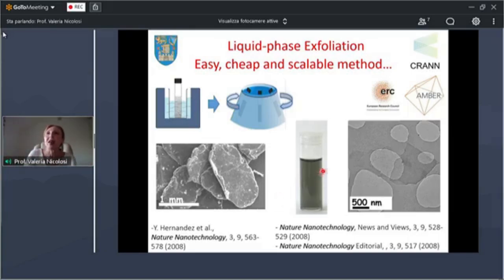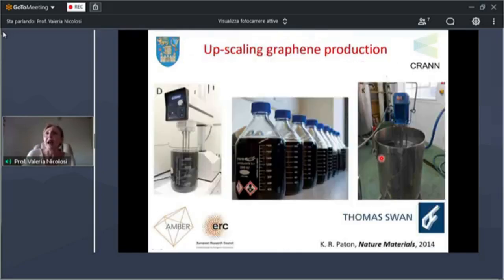So we did develop this for graphene, of course, a material that back then had just been discovered by the Scotch tape method. And we found that really what we could produce was very nice, large, two-dimensional sheets and with a variety of different thicknesses, but the majority of them being a few layers thick. This changed the way we process these materials, of course, and opened a lot of different avenues of what we can in reality do with these systems.